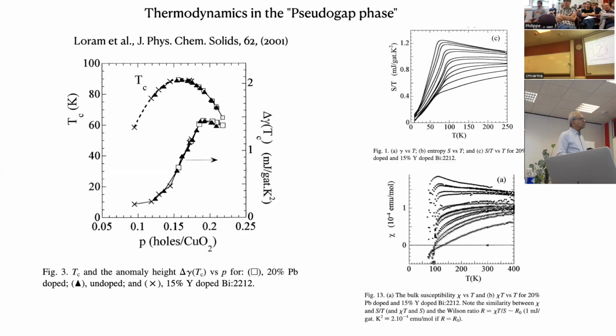And here's an interesting plot. If you look at the jump in the specific heat at the superconducting temperature, it begins to diminish around the doping where the linear resistivity is dominantly seen to the lowest temperature. This sort of suggests that this loss of entropy already in the pseudo-gap phase is reflected. You've already lost some electronic degrees of freedom, and it's reflected in having it's a measure of the superconducting condensation energy in some sense. And TC is doing something like that. So I'm giving you the basis for that phase diagram and the important changes.